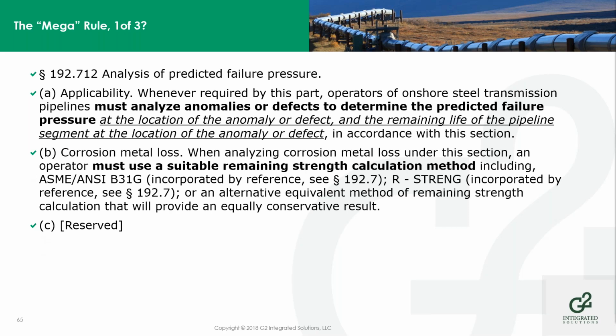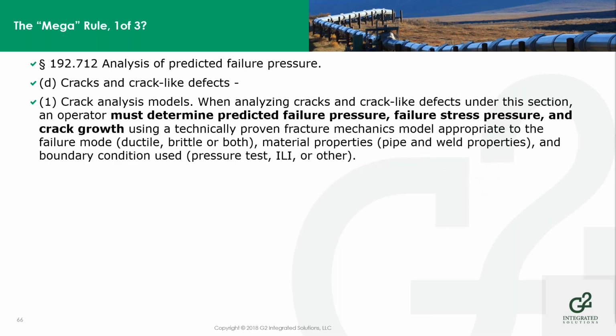Applicability of 712, predicted failure pressures. Operators of steel transmission pipelines must analyze anomalies or defects to determine the predicted failure pressure at the location of the anomaly or defect and the remaining life of the pipeline segment at the location of the anomaly or defect. You must use a suitable remaining strength calculation, either B31G, R-STRENG processes, or an alternative equivalent method of remaining strength, provided an equally conservative result is reached. Crack and crack-like defects have to be considered and you must determine the predicted failure pressure using a technically proven fracture mechanics model. And again, this is going to be at the location where the condition exists on the pipeline.